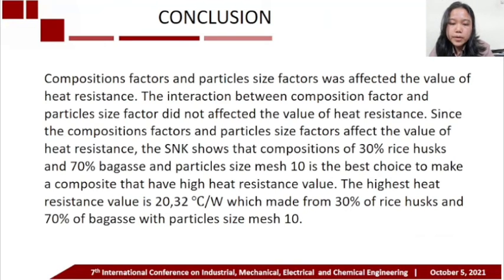The conclusion of the experiment is that composition factors and particle size factors affected the value of heat resistance. The interaction between composition factor and particle size factor did not affect the value of heat resistance. Since the composition factor and particle size factor affect the value of heat resistance, the SNK shows that the composition of 30% rice husk and 70% bagasse and particle size mesh 10 is the best choice to make a composite that has a high heat resistance value. The highest heat resistance value is 20.32 degrees Celsius per watt, which is made from 30% rice husk and 70% bagasse with particle size mesh 10.